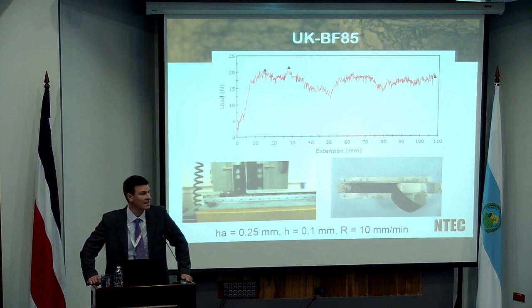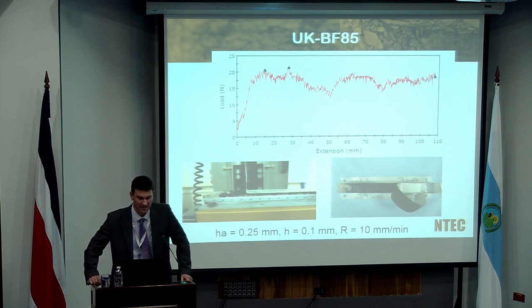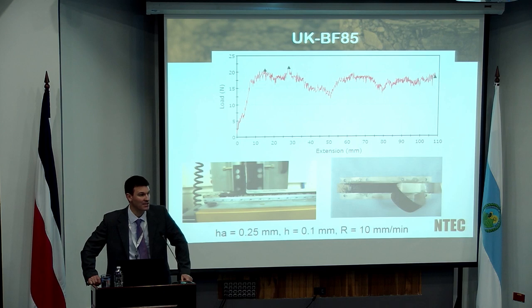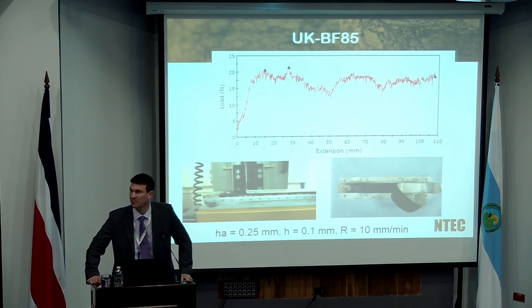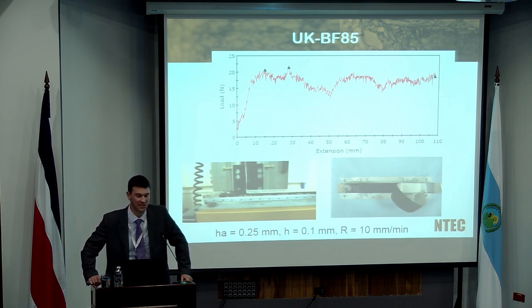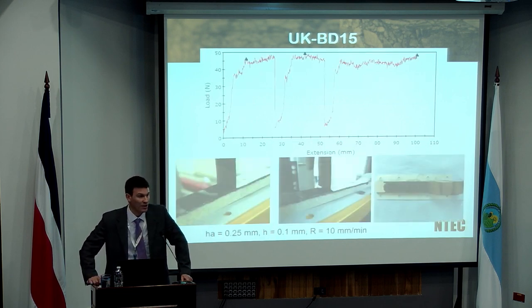And then straight away, you start getting values, initially a load. So if you're doing a constant displacement test, and all the tests for this particular example were done at 10 millimeters per minute, we would peel off that aluminium peel arm off our substrate and bitumen combination, and we would measure a load. So this was a relatively soft binder. The 85 refers to the penetration grade, so this is a soft binder that you would probably want to be using as a surfacing binder in a surfacing material. And you get values, and it varies slightly, of about 20 newtons as your force required to peel off that particular combination. We could play around with that, and we did.